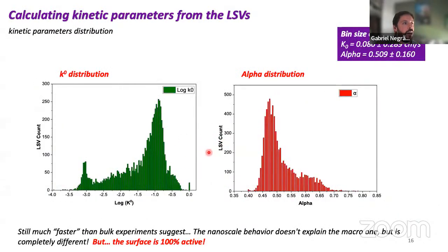But if we do a histogram distribution of those values, we can see again that some pixels are quite fast, as fast as gold, as we expected here, when K0 is a very high value. This is log K0 again. And then we have this, which looks to me like almost 3 groups here. We have a very slow one, we have a broad one here, and then we have a very sharp group here. So the average behavior is roughly here. So it's fast, but not fast-ish. So this is the average K0.